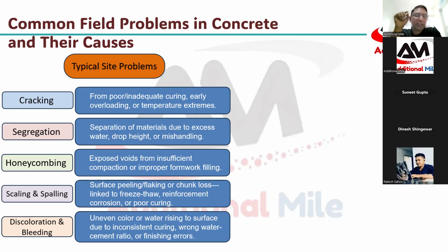Scaling and spalling. As I told you, we use excessive tamping and finishing on the floor. After some days, we can see surface peeling, or we always call it flaking. Or sometimes in very heavy cold, I don't think someone is here from the Kashmir area, but in a colder region, concrete sets very fast before even doing proper vibration. So those lumps will remain there, and once the load comes, that gets cracked. Sometimes it is poor curing: one side we do the curing, one side we forget the curing. So on that side, the surface starts losing its cement finish.